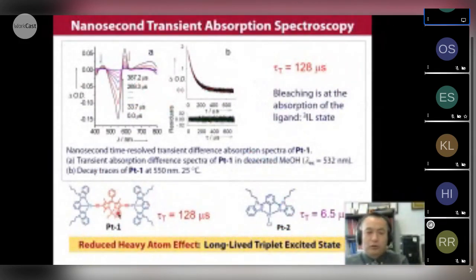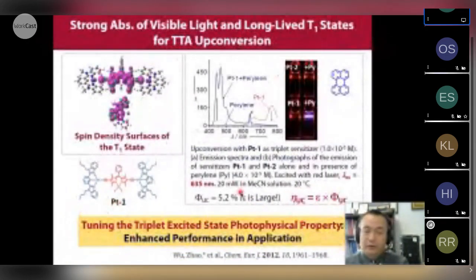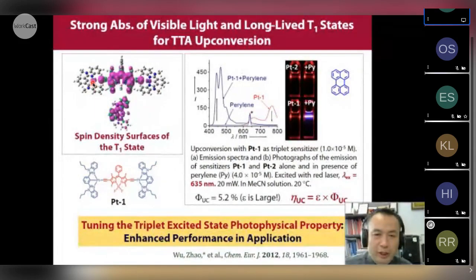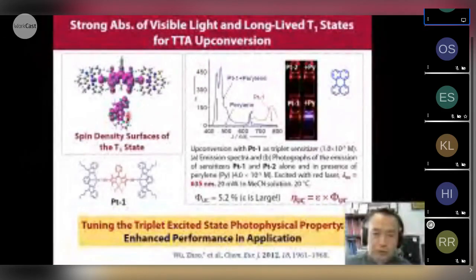The triplet lifetime of the new complex is also much longer than the model one because we have different triplet states for the two complexes. For the new one, we have a pi-pi triplet state, but for the model one, we have an MLCT triplet state. They have different spin orbital coupling, then they have different triplet state lifetimes. This is the spin density of the T1 state. We can see for the new one, we have very small contribution from the metal, but for the model one, we have a larger contribution from the metal. That will reduce the triplet lifetime.